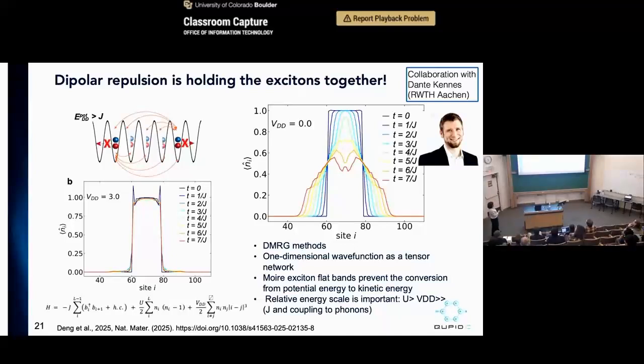So what he did was he first created a Mott state, and he ran 2 cases. One is without the long-range dipolar interaction. The other is with the long-range dipolar interaction. It turns out that if you don't put in the long-range dipolar interaction, because our sample is about 10 microns, and our beams are about half a micron or so, you always have edges that are still empty. So if you don't have long-range repulsive interaction, like a dipolar interaction, the excitons would quickly just move out to the empty sites on the edge. So your Mott state will form, but it will melt very quickly. But interestingly, if you start to dial in dipolar interaction, then they stick together much longer.